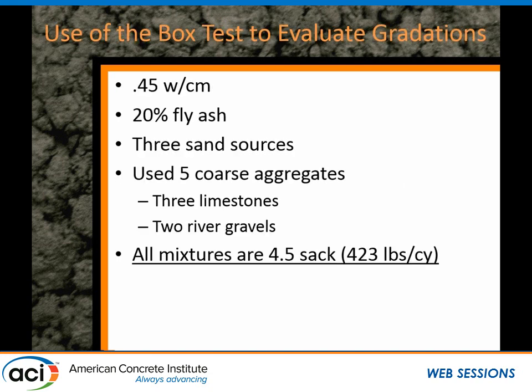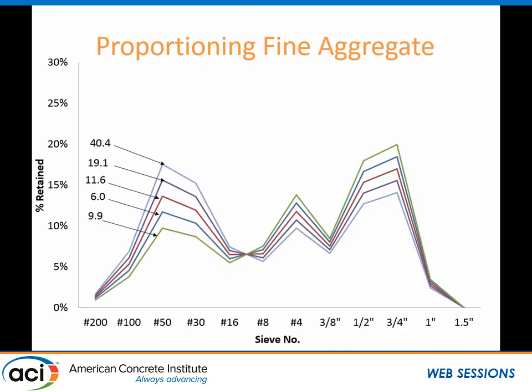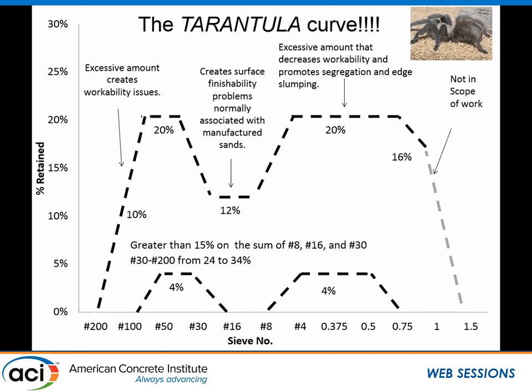So we've kind of built something cool — a tool that can evaluate concrete mixtures and give us some insight. Is the 8-18 curve the best? Is there something better? We're using 0.45 water-to-cement ratio, 20% fly ash, three different sand sources, five different coarse aggregates, and four and a half sacks of total cementitious material — a very low paste content. We can teeter the intermediate to the coarse, change the fine, teeter it around. We've learned a ton of stuff that's all published. We've come up with something we could take all our recommendations together — we call it the tarantula curve.